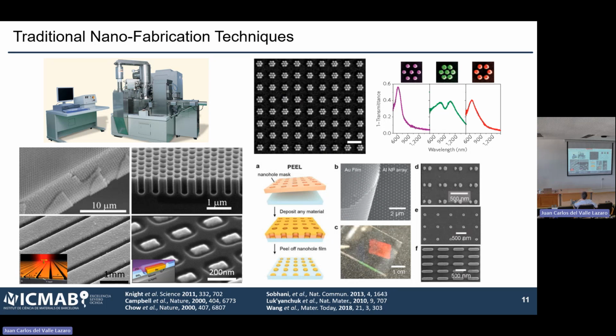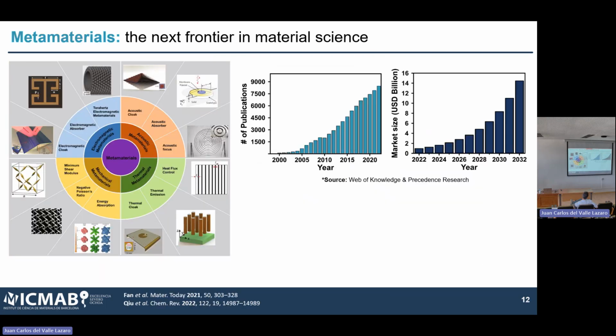So traditionally, these structures have been fabricated using nanofabrication techniques, so electron beam lithography and metal evaporation. And this has been very great for understanding their optical properties and studying the system, understanding how they behave from a physical and optical point of view. But lately, the field of metamaterials has been moving to a new phase where people start to look at, okay, can we use this to do what they call the chemistry of metamaterials? So start to use this system to interact with the chemical environment and, for example, use these resonances to run reactions, do photocatalysis, or things of that sort.